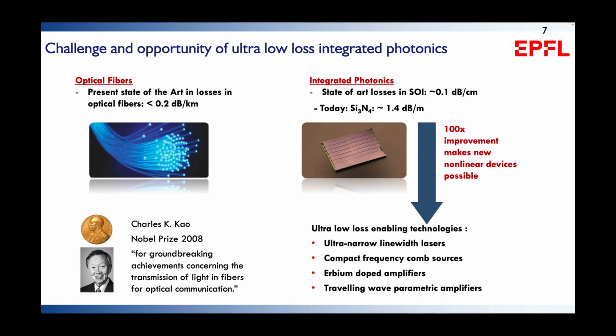The first question I can answer is, we've demonstrated 1 dB per meter in silicon nitride. It's a fantastic value. 10 years ago, I would never have thought this is possible. But the question is, what is the ultimate limit of silicon nitride? Without going into how they work, we have made measurements of the residual absorption of the material. And it turns out that we are more than 2 orders of magnitude away from the fundamental limits of silicon nitride. Based on the optical measurements we have made, silicon nitride should support losses of 0.001 dB per meter, so basically 1 dB per kilometer loss.